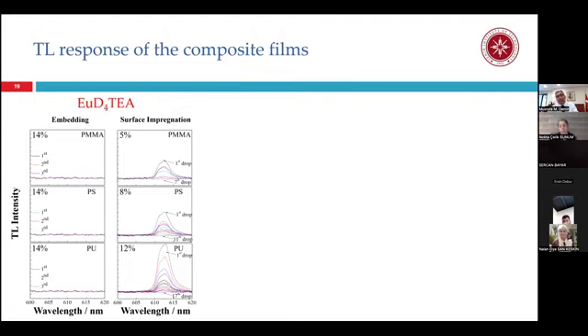Easy to understand, the triboluminescence is associated with the crystal, not molecules. In solution, we have a molecular dispersion of the triboluminescent compound, and we don't have triboluminescence performance. In surface impregnation, we do have a triboluminescent signal in the first drop, and we apply second, third. In the first 7 drops, we observe a triboluminescence signal, okay?